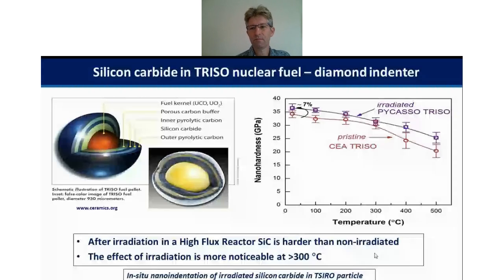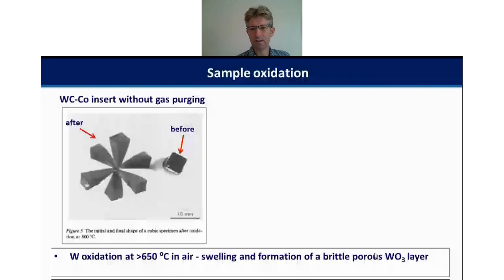So it is, as I say, quite a successful material. This is an example using diamond as an indenter from Manchester University, and here they've tested a so-called Triso nuclear fuel pellet. They've tested the silicon carbide layer in that material, and then looked at the effect of irradiating that to simulate what might happen in a nuclear reactor. And what you can see is that you can effectively get reasonable mechanical property data across that temperature range to 500, and you see a softening without any particular increase in data spread.